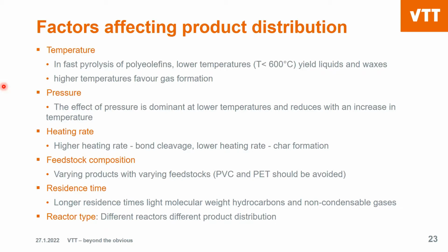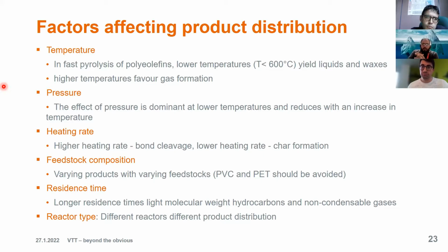Feedstock composition, which means what kind of feedstock is welcome for pyrolysis. As I said, it welcomes heterogeneous types of plastic waste. It can have polyolefins and others, but preferably PVC and PET should be avoided in the plastic mixture. PVC tends to degrade into chlorine, and PET tends to degrade into acids. So these two polymers should not be in large quantities in the feedstock,